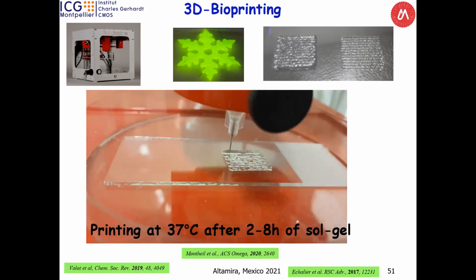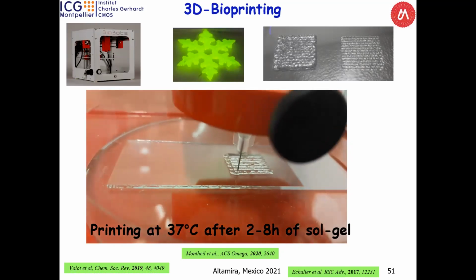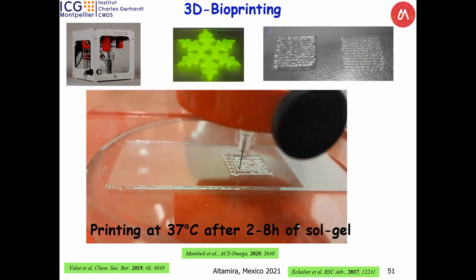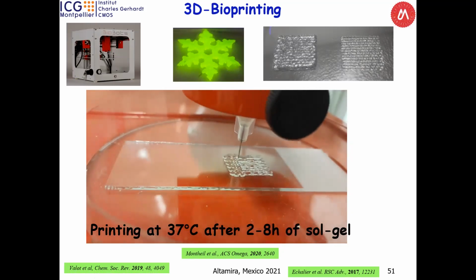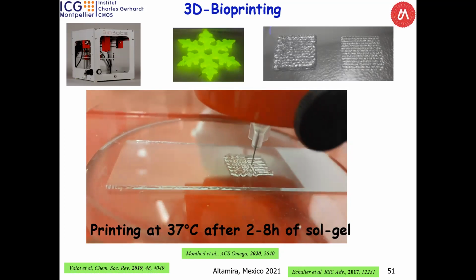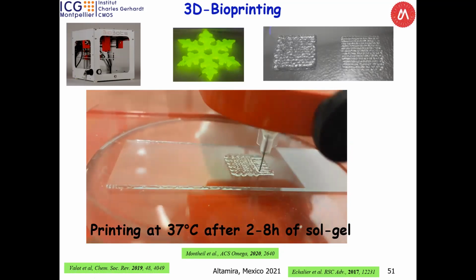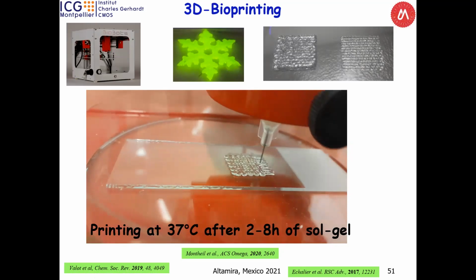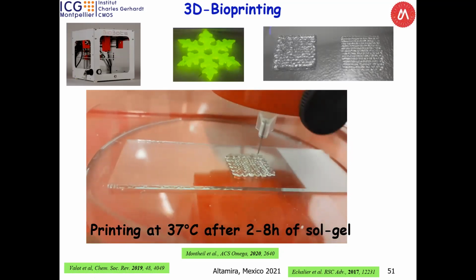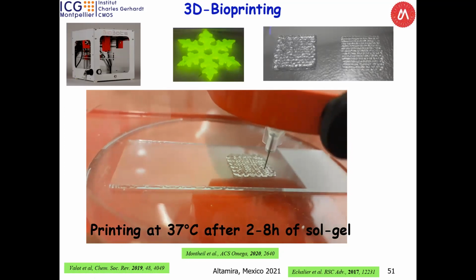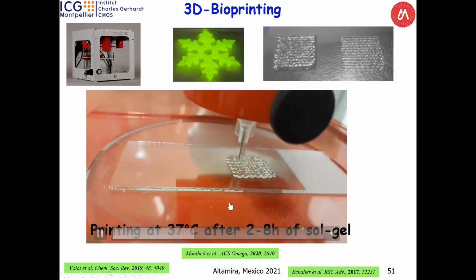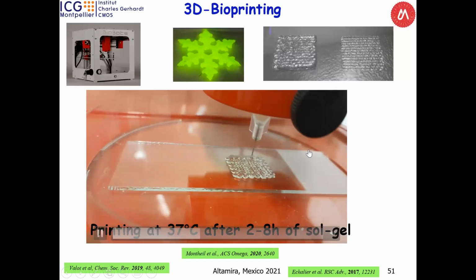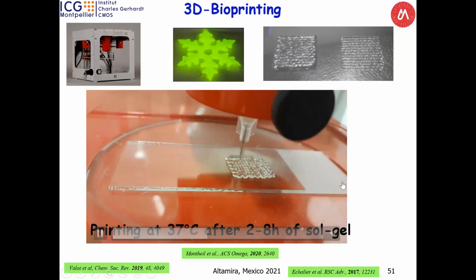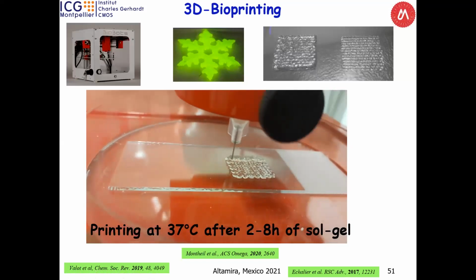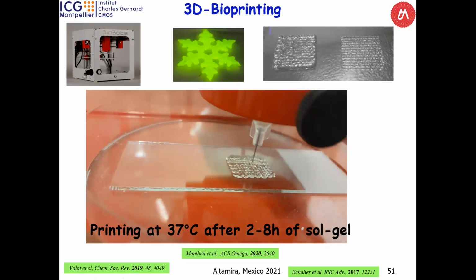But look, you can control. In general, we have between 40 minutes and 1 hour 30 to do the printing. If you wait more than this time, it's not possible to print it because the viscosity increases. Now, you know, we can make several layers one by one without any problem.